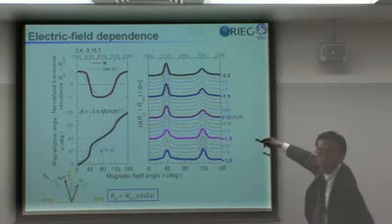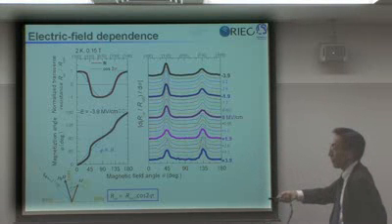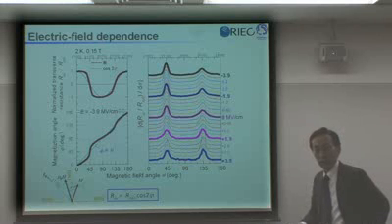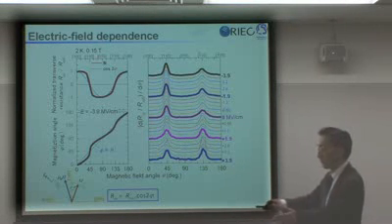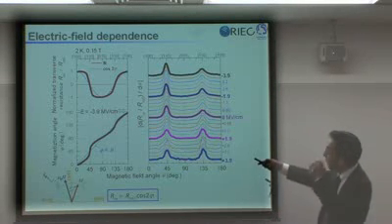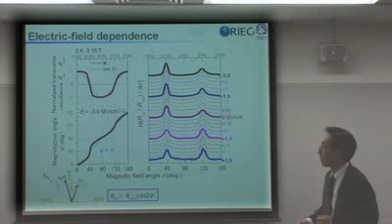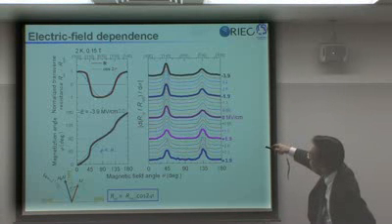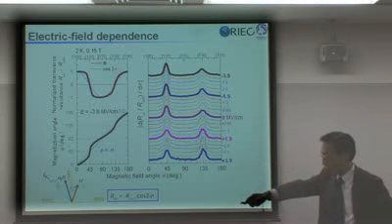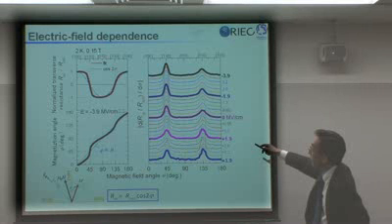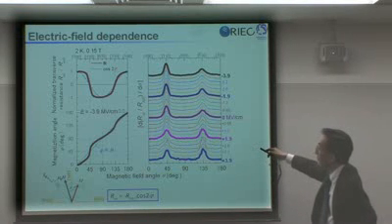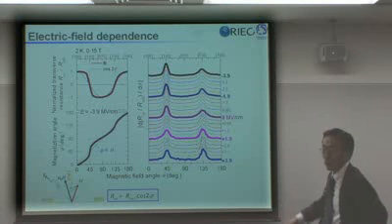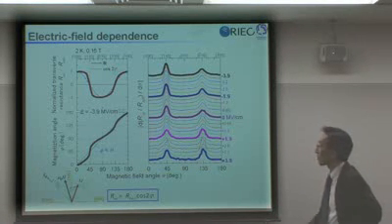So this blue dotted line is the line you expect for the materials that do not have anisotropy. Or if your magnetic field is strong enough, you see that there will be cosine 2 theta. But here you can see that it is not. The black one is experimental data, and when we change the direction of magnetic field, which is 0.15 Tesla, the experiment was done at 2 Kelvin, it's not like cosine 2 theta, but you can see that it is skewed.